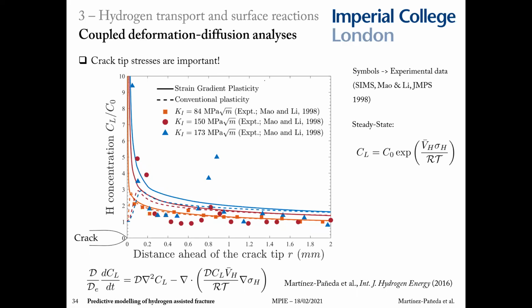In fact, as you can see in the slide, experimental measurements of hydrogen concentration ahead of the crack tip agree better with the predictions from strain gradient plasticity and show two effects. The first one is that hydrogen content increases with the remote load, which is only captured with strain gradient plasticity. And second, the hydrogen content increases as we approach the crack tip, which again, you can only capture if you enrich your continuum model.